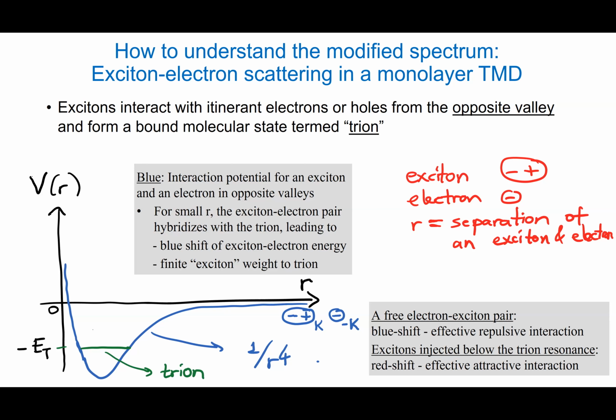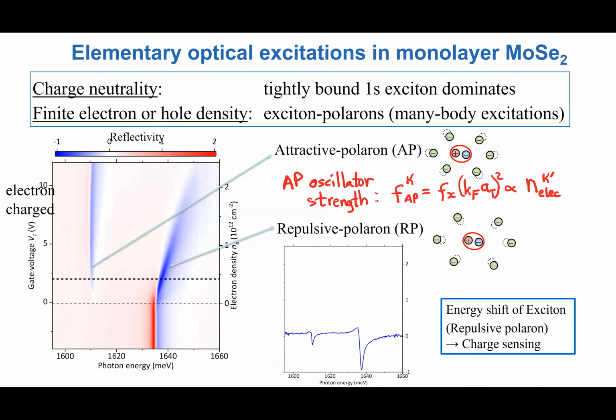Because then the energy penalty for virtually occupying or mixing with the molecular state is going to be smaller. Now, at the same time, this molecular state, which is optically non-observable, it doesn't have an oscillator strength, because of the hybridization, it picks up an exciton character. It picks up the scattering state character, which actually is optically accessible. That's our exciton polarization wave that we generate. So the net result is that this molecular state is going to redshift while picking up an oscillator strength. Okay? So therefore, the two resonances that we have seen are these two states.